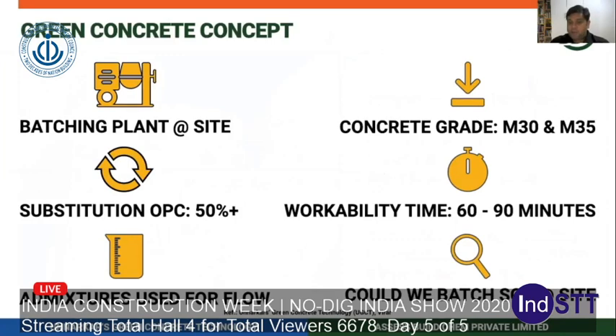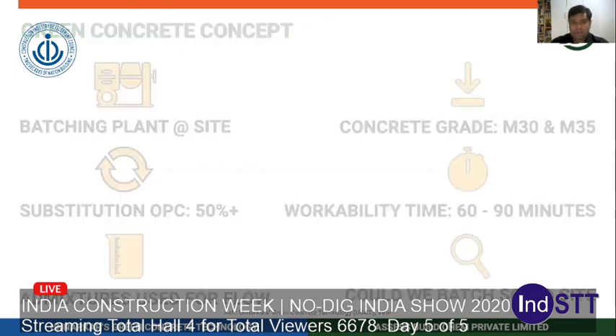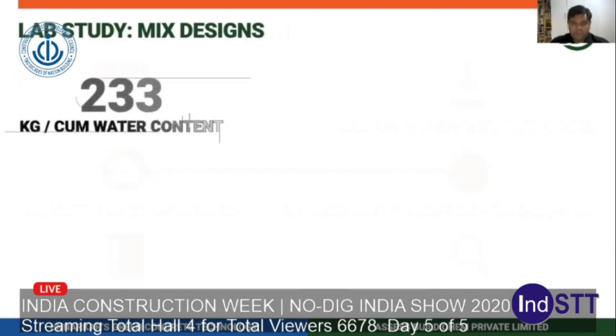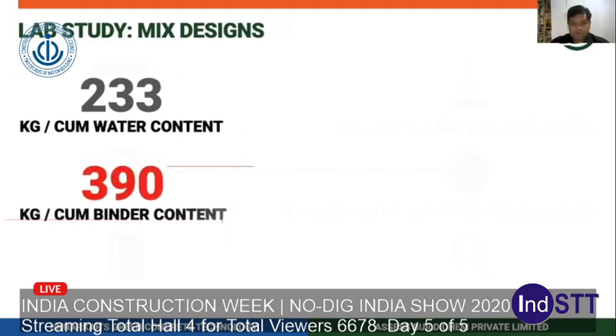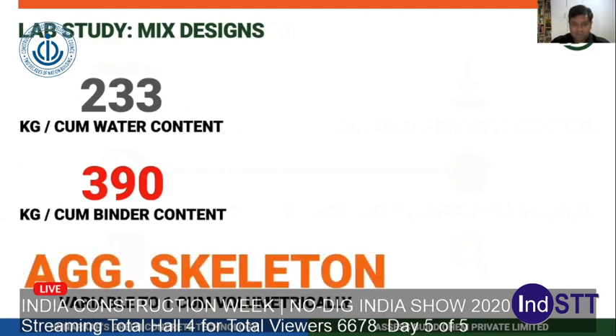And this led to a new idea: could we batch the SCC at site? The reference for this, of course, came through Unarkar's green concrete technology. That's the name of the firm at Virar. So from there, the first step was to see how the concrete performs on its own. Basically, a water content or water cement ratio was fixed. We used 390 kgs of binder and 233 kgs of water, so the water cement ratio is a little bit more than 0.5. There were no admixtures used in the initial study.